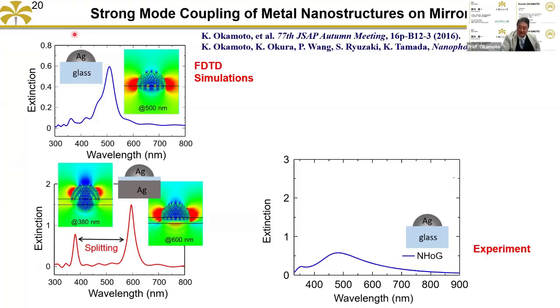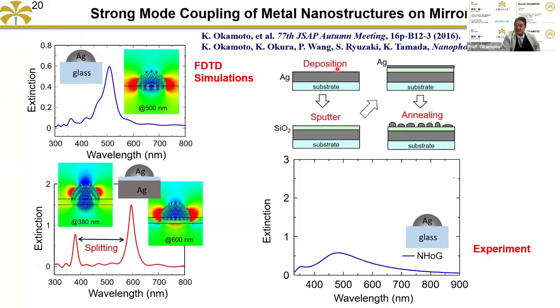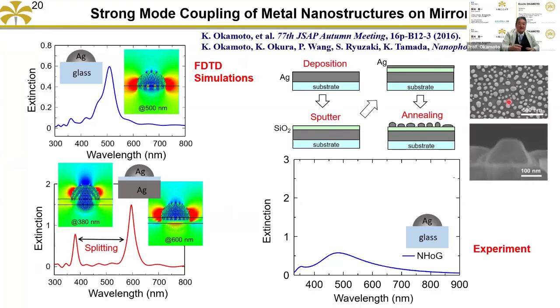And that's a calculation. Then we can fabricate this structure by the deposition of the metal, sputtering the dielectric material, depositing a very thin metal film, and thermal annealing. Such a random structure is very easily fabricated by thermal annealing. When a thin metal film is heated, it automatically forms a random metal structure, not aligned, with a hemisphere structure.